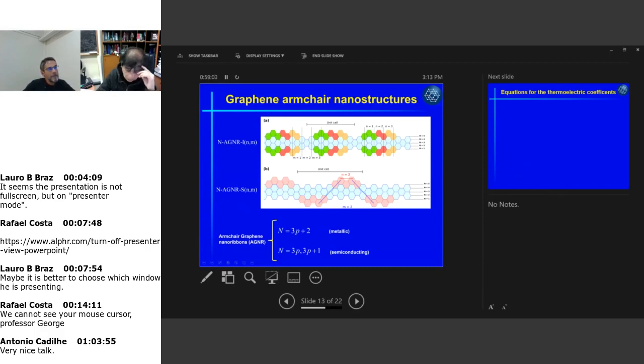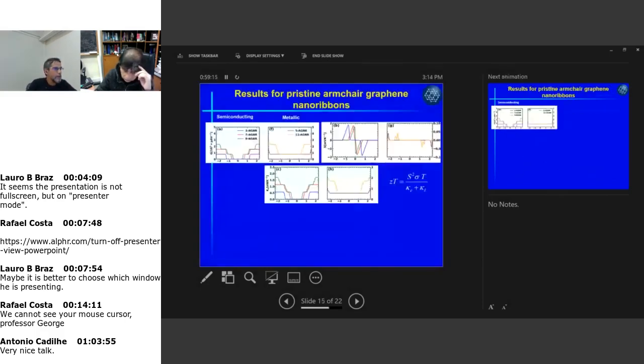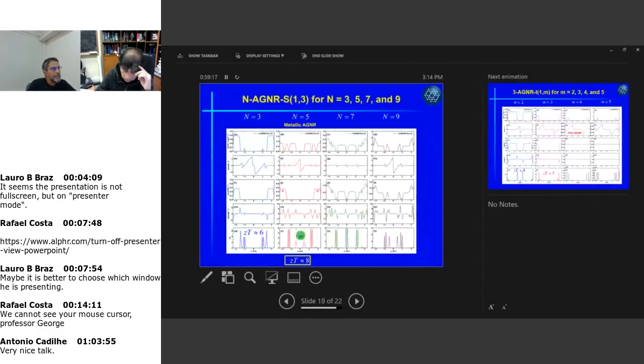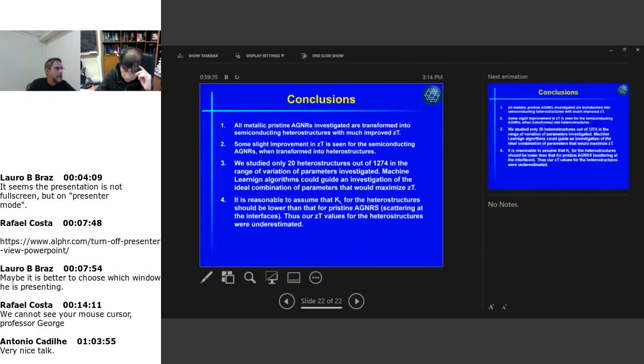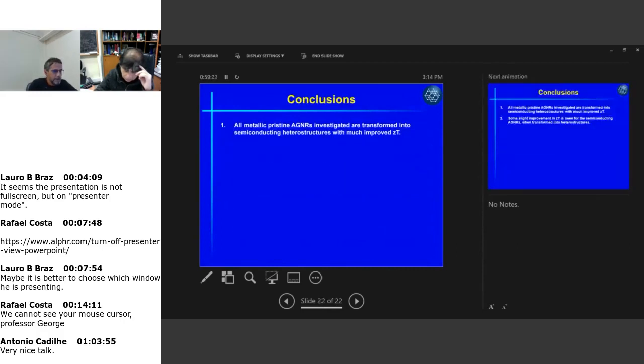And if you have scattering mechanisms here, the ability of phonons to transport heat will decrease, therefore kappa L is going to decrease. So our results here for the ZT are underestimated, because we expect that kappa L is going to be smaller for the heterostructure. So I finish here quickly. All metallic pristine AGNR investigated are transformed into semiconducting heterostructures, with much improved ZT.